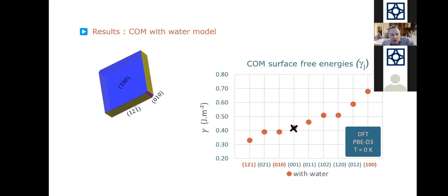But what does it mean? That means that our surface energy here is in fact too big, too high. So we have to destabilize this surface, in order to be sure that it is not interfering with the other surfaces. And this means that this system is probably inhibited kinetically.